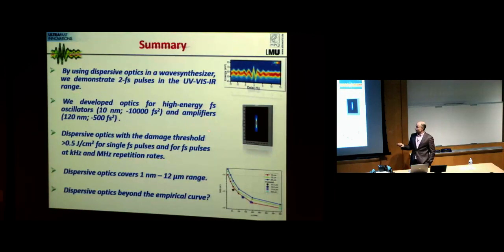Actually, we have a lot of freedom in designing the mirrors. We can design mirrors with a very narrow bandwidth, with minus 10,000 femtosecond squared. The damage threshold for our mirrors is also an issue, and at the moment it's somewhere in the range of 0.5 joule per square centimeter. The mirrors which we produce cover a range from 1 nanometer to 12 micrometers.